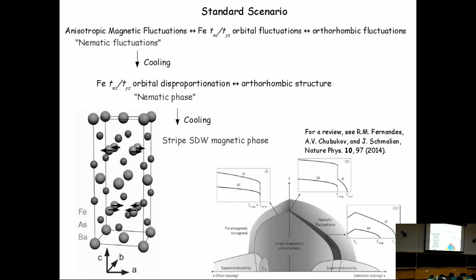Well, I'm not sure. That's a point that we do not make. I'm not sure if our results mean that we are favoring the magnetic mechanism as the driver for this set of transitions. We saw that the nematic fluctuations have a maximum at a temperature which is slightly higher than the magnetic ordering temperature, but doesn't match the orthorhombic phase transition temperature either.